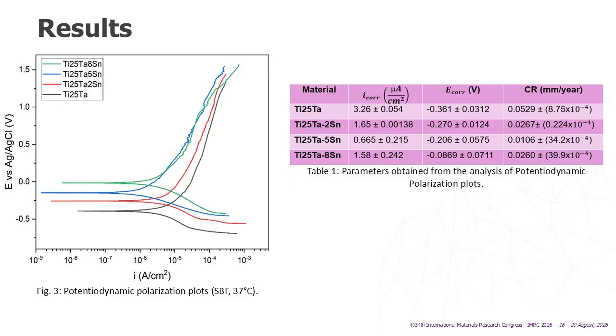The current density and corrosion potential values were determined using the Tafel extrapolation method, and the corrosion rate was calculated in millimeters per year. These parameters confirm that the materials containing tin exhibit lower current density values and corrosion rates, between 2 and 5 times lower than those of the titanium 25 tantalum alloy. The alloy containing 5% tin, which exhibited great stabilization of this phase, showed the best corrosion resistance, with a rate of 0.0106 millimeters per year.